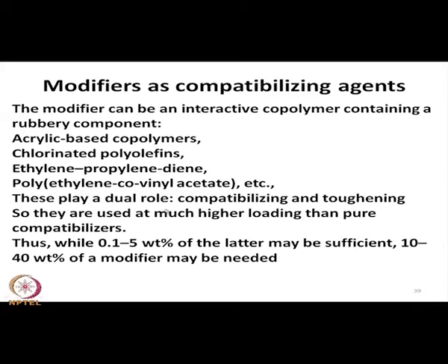So, since they increase compatibility and, along with increasing the compatibility, they increase the toughness of the polymer, these polymers are used at much higher loading than pure compatibilizers. Thus, while 0.1 to 5% of the compatibilizers may be sufficient, in this case 10 to 40% of a modifier may be needed to modify the properties of such polymer blends.